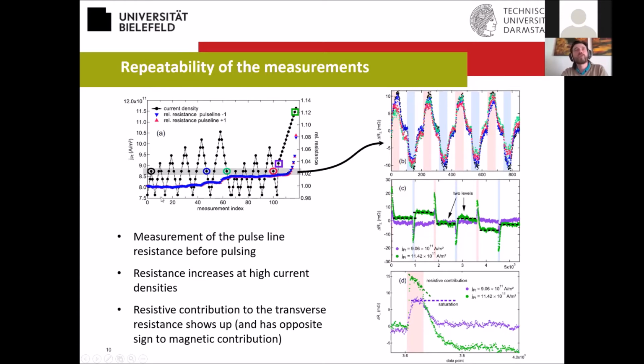This is what we got. After these cycles, we have this blue, black, green, and red traces here, and they look pretty much the same, which is good. But as we go to higher current densities, here in violet and another green, we see that for very high current densities, we get this strange two-level behavior of this relaxation part. When we zoom in, we find that during the switching phase, it doesn't saturate anymore. But actually, we see that now this response goes down.